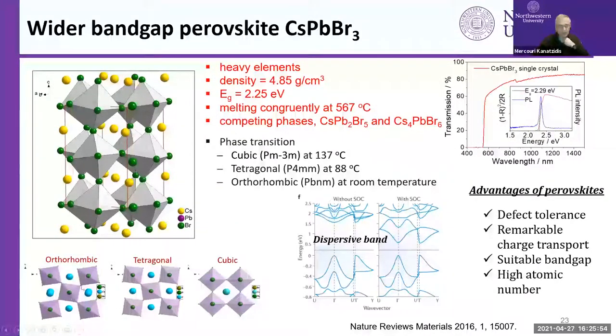For example, this material is orthorhombic at room temperature, because the octahedra, in this view you can see, have been rotated compared to high temperature, where you see the octahedra are not rotated and the lead-bromine-lead angles are straight. This is the ideal structure. And then when you cool it down, you get a rotation of the octahedra, it becomes tetragonal, then further rotation becomes orthorhombic. These are phase transitions. Normally, phase transitions, when you try to grow crystals, are not desirable. Actually, they are bad news. In this case, these transitions are mild and they're not catastrophic. So they give you a material that is twinned, but it can still work.